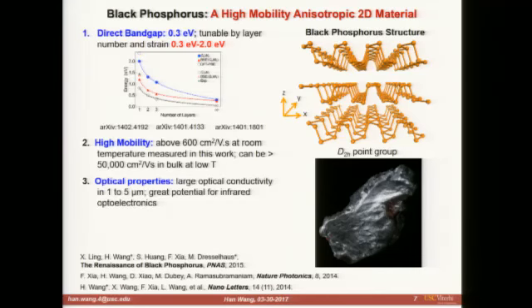The material also has strong optical responses in the 1 to 5 micron wavelength range, corresponding to its 0.3 eV band gap. It's very interesting for exploring infrared optoelectronic devices.